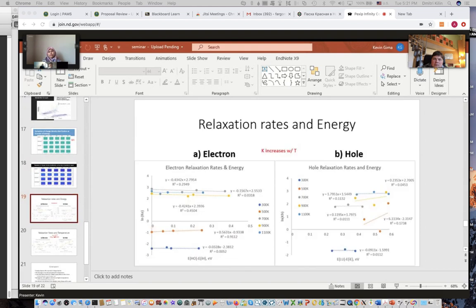All right, and then next we have my electronic relaxation rates and energy. So I'm studying to see how my relaxation rates change with energy. And I'm also seeing how well they correlate with the band gap law. So for my electron relaxation rates, I can see that there's a moderate correlation here with the band gap law, as my R squared values demonstrate. And then for my hole relaxation rates on panel B, I can see that there's little to no correlation with the band gap law.